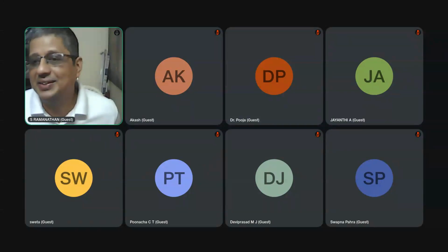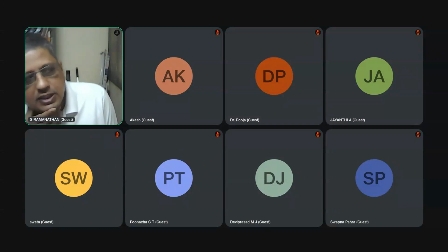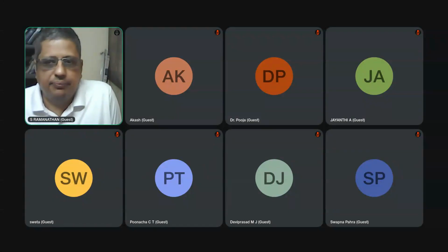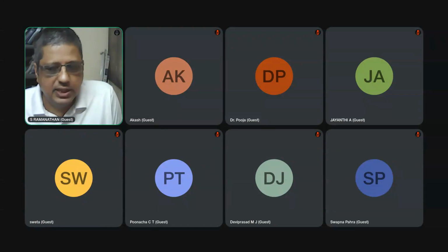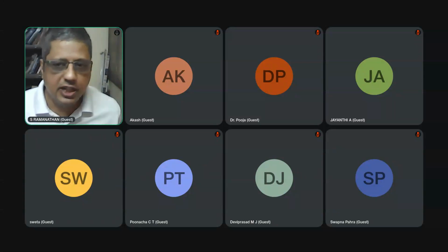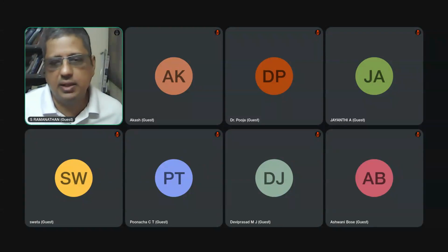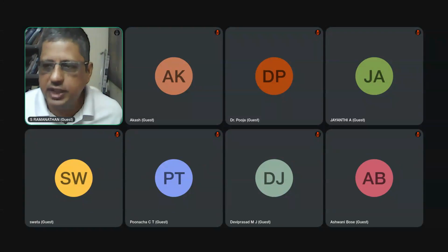Okay, I'm sorry. Can Tafel slope interpreted data be used for modified electrode rates of degradation rate? See, first, the problem in Tafel analysis is this. Okay. When I say problem, I mean what I have observed is usually people use the commercial software. Okay. They would draw the lines. Some of the commercial software doesn't tell you necessarily how good the fit is. That is, you're assuming Tafel equation is applicable to that current voltage system. But if the fit is poor, we can't even use that analysis. If the fit is good, then only we can interpret the data. Okay? So let us assume the fit is good.